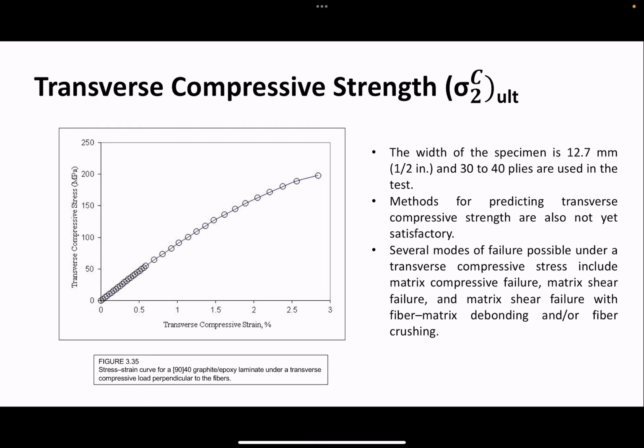And then we come to the fourth value, transverse compressive strength. Again, you have a particular standard to follow. Let me check if there's a standard given. It's the same standard D3410, but I believe the width is different, and in order to strengthen it, we use 30 to 40 plies. And similarly, here also analysis models are not satisfactory. It gets more complex. But that's why we prefer experimental analysis here. You use the same standard, same kind of compression test, but the specimen details are different. And then you record stress and strain, you draw the graphs, and then you get values.